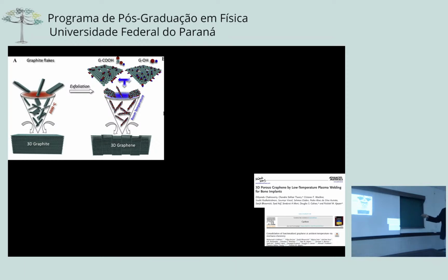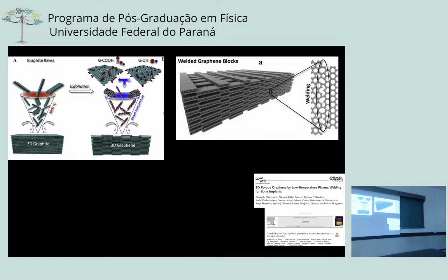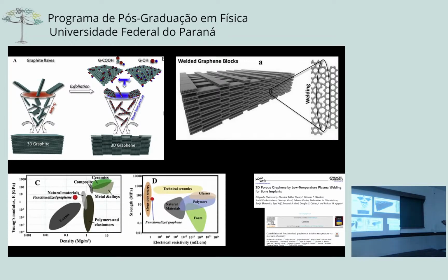When we say functionalization, we do a chemical functionalization. If you do the right chemistry, you functionalize them, put them together and compress it at a temperature like room temperature or around 200 degrees centigrade, you can weld them and make a porous structure with good rigidity, good mechanical strength and good conductivity. Now with graphite, if you are using it for any heating source, conductivity is a big problem. If you want highly aligned graphite, it means you'll have good electrical conductivity, but the cost increases because of processing conditions, you have to anneal for a very long time. There are several processing challenges. But if you do this graphene route, we can make them at room temperature or around 200 degrees centigrade.